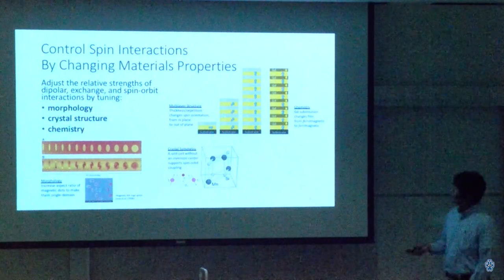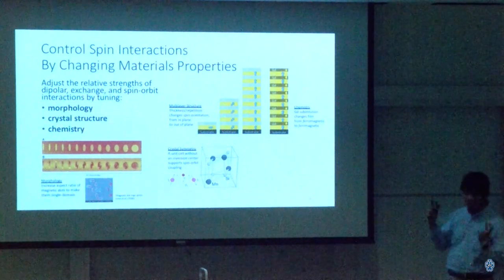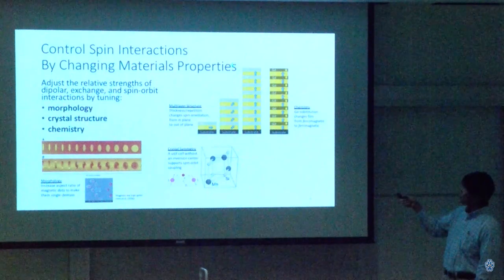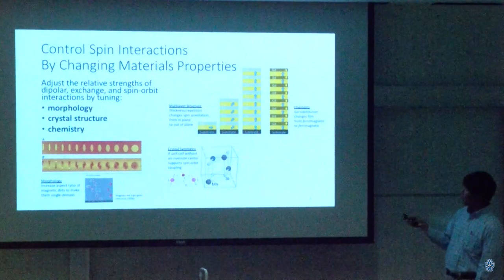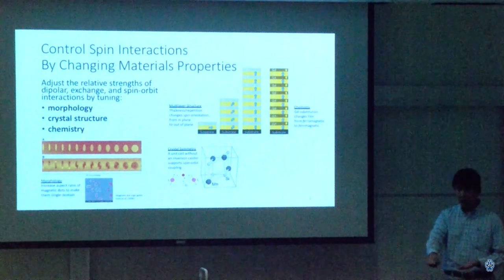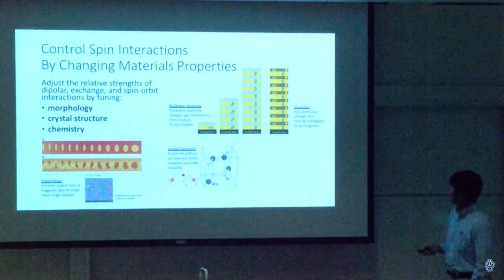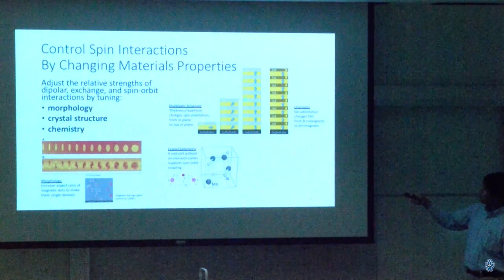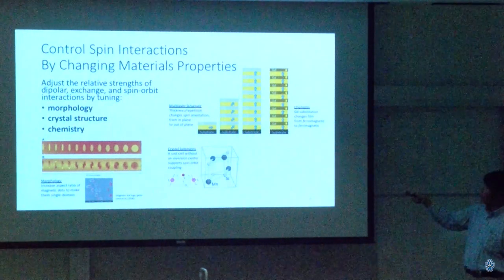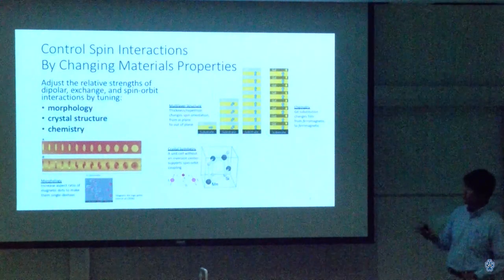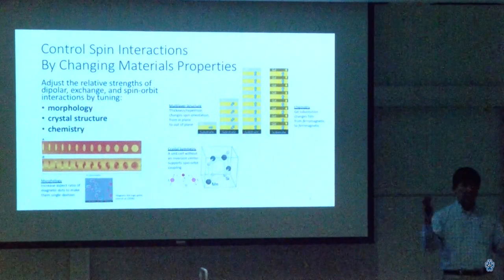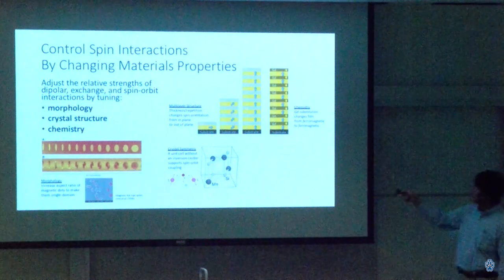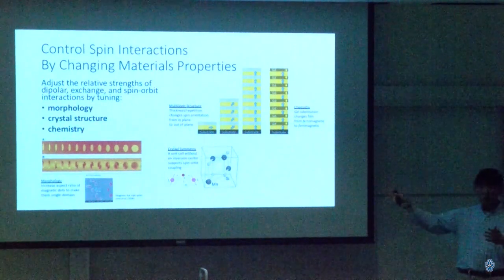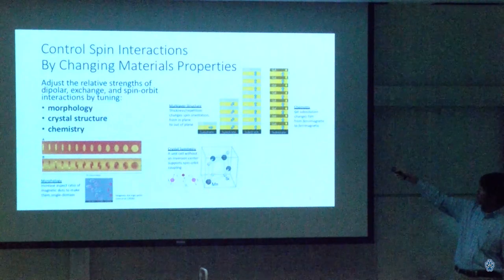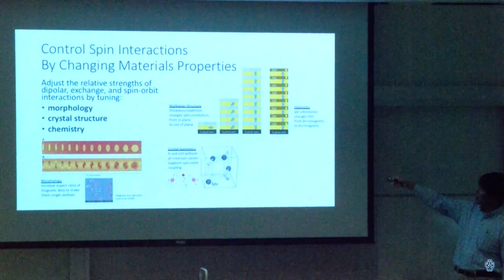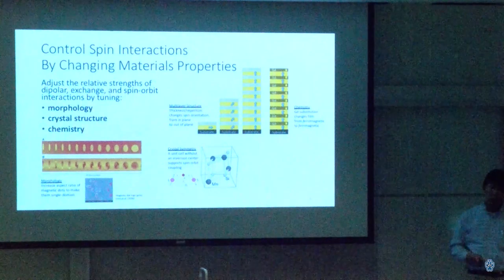Yeah. So with an artificial crystal, as it were, by just changing how the layers are applied, you can get the magnetic moment of a thin film to either point horizontally or vertically. Or by changing the chemical used in the gray layer from, say, palladium to gadolinium, it can cause the material to go from being ferromagnetic, in which all the magnetic moments point in the same direction, to being ferrimagnetic, in which there's a net moment in one direction, but you can see that the magnetic moments on the gadolinium layers point in the opposite direction to that of the cobalts.